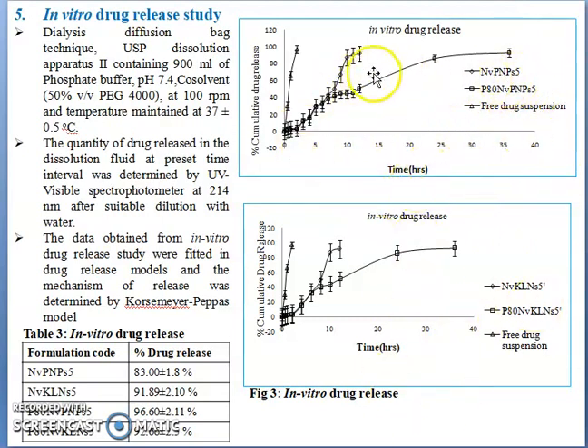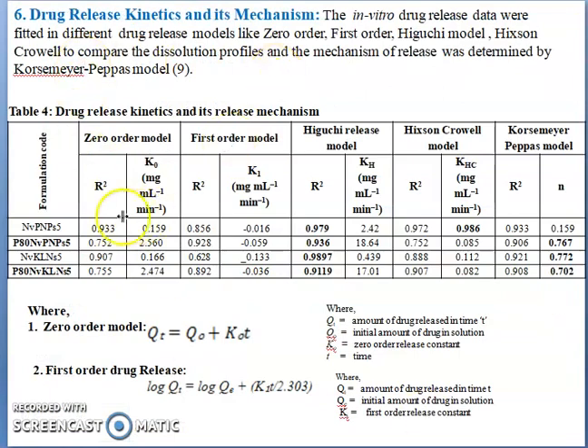In the case of polymeric nanoparticle, the uncoated one could release only for 12 hours, whereas the coated nanoparticle releases up to 36 hours. So there is an increase in the drug release. So you can say 83% drug is released for polymeric, and for coated polymeric 96% in 36 hours. So the amount of drug release was extended for 36 hours. Similarly, for lipid nanoparticle also we can see 12 hours, and in lipid also we can see 91% drug was released in 12 hours, whereas after coating 92%. So in this case, the coated polymeric nanoparticle releases more quantity of drug in 36 hours in comparison to the coated lipid nanoparticles. Then drug release kinetics, I already told.